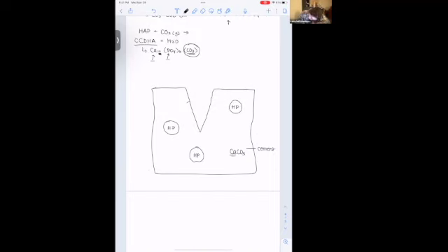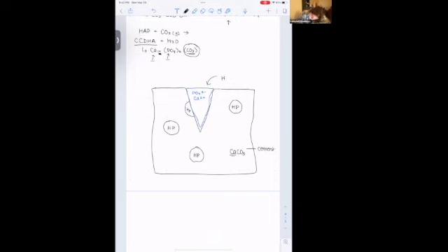And when the crack starts to form and it hits one of these HP spots, the hydrogel will begin to release phosphate out. And so in this crack, you end up getting a population of phosphate molecules. You have calcium available. And then from the environment, you can have water coming in and you can have carbon dioxide coming in.